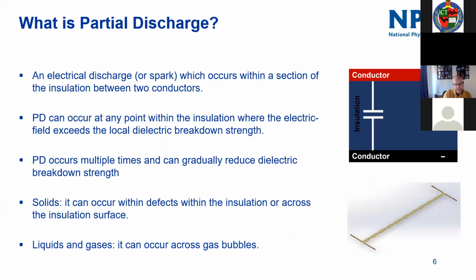One of the issues that we're looking to understand better at the moment is a phenomenon known as partial discharge. So this is where you don't get to those voltages, you don't get to your 3 kilovolts per millimeter, but you can still get a small electrical discharge or spark occurring within the insulator between two conductors. And particularly where that dielectric is organic based, that can lead you into problems.